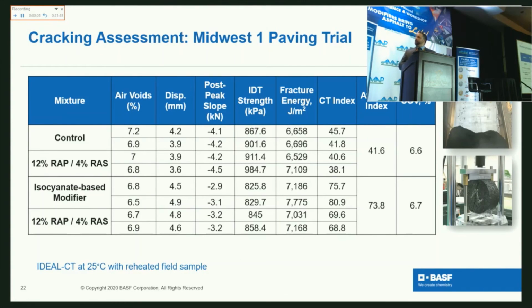So the other finding that we had from this trial as well was with Ideal CT, Phil took and tested that, and we were able to see just with this additive. So the additive loading on this trial was only 1%. So essentially what the customer was looking for at this point was, hey, can we take our 5828, just improve it to a 6428 and pave with it? So we just did it at a 1% loading level.